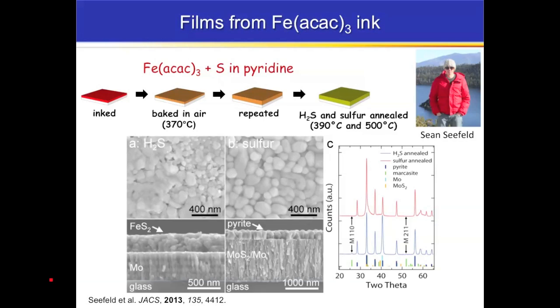This is a film that's been sulfurized. So the pyrite film is very thin compared to the moly film. And actually, during the sulfurization process, some of the moly is converted to moly disulfide, and so the moly film swells by about a factor of 3 or so. And so these thin film materials, as I'll show in a minute, doesn't matter how we make them, we get pretty much all the same kinds of electrical properties.